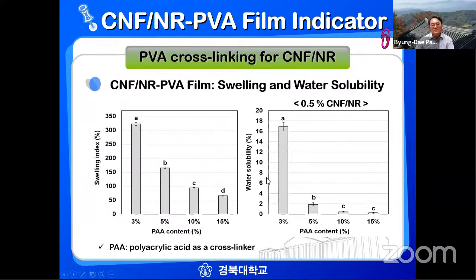And also we checked the swelling and the water solubility of this film. As you see, as the PAA concentration increases, the swelling decreases. That means when you cross-link more, you have less swelling of the film. And also you have much less water solubility when you have more cross-linking agent in the PVA. But 3% is a little bit soluble. This is kind of typical for this kind of PVA polymer as a matrix. Anyway, 3%, 5% is what we tried to make the composite material.